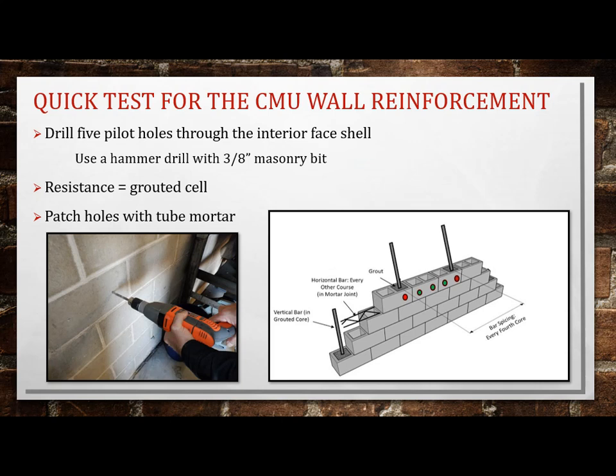So I came up with the 5 pilot hole test. You take a hammer drill with a 3/8 masonry drill bit, and you drill a hole through the face of a block in the center of the cell. If you hit resistance, it's grouted. Plus the powder will change. As you're drilling through, the block will give you one color powder. As soon as you hit the grout, the powder changes. So you're in grout. That doesn't guarantee there's steel in there, but you hope if they grouted it, they put steel in it. There's a technique later on where I'll show you how you find reinforcing steel.